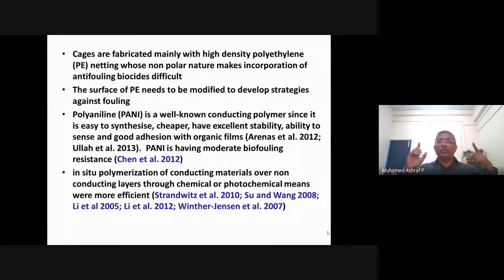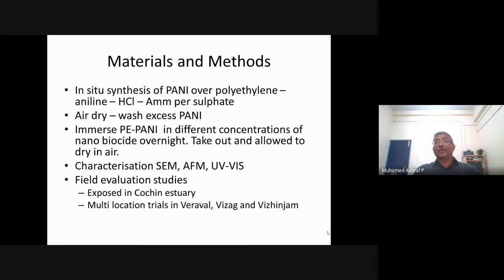What we have done is we have modified the surface of the polyethylene nets by using another conducting material called polyaniline. It is a well-known conducting polymer, and it is easy and cheaper also. So we have made a methodology to change the surface of the net using polyaniline. Over this conducting polymer, we can easily incorporate nano copper oxide or any other biocides. We have done it by in situ polymerization, and we have incorporated nano copper oxide. These are the materials and methods we have used for that.